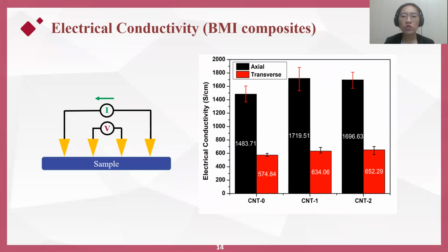To characterize the electrical improvements, a 4-probe configuration was set. Similarly, a substantial difference in the electrical conductivity along the 2 directions was found, once again indicating partial CNT alignment. We see that both water-assisted groups, the CNT1 and CNT2 composites, showed higher electrical conductivities at around 1700 Siemens per centimeter, which is about a 16% increase when referenced to the CNT0 composites.